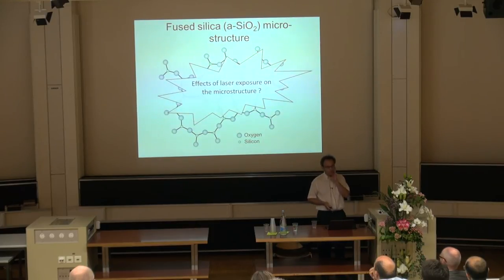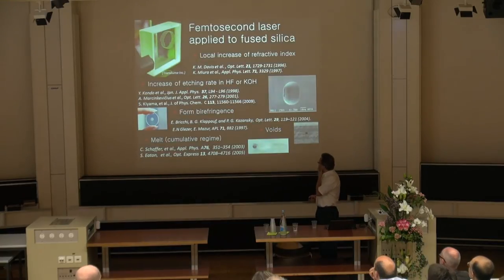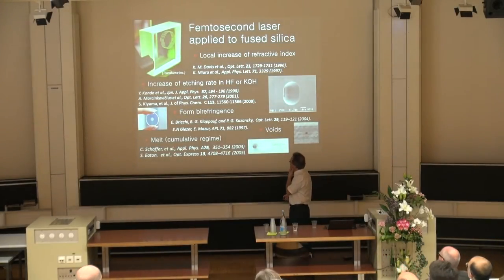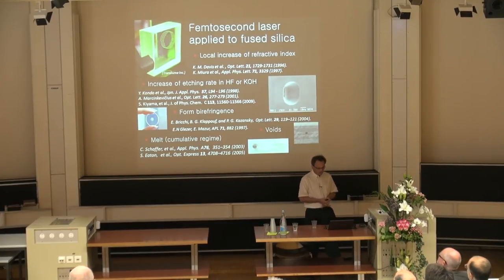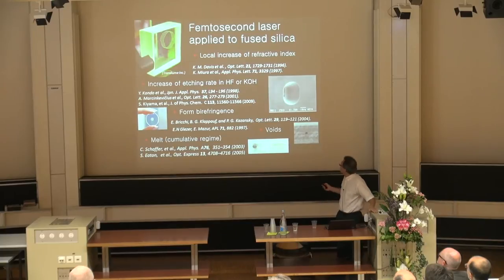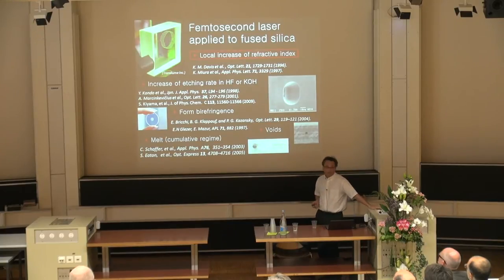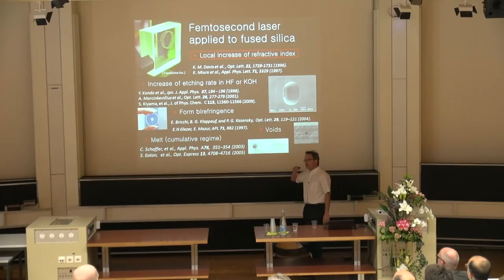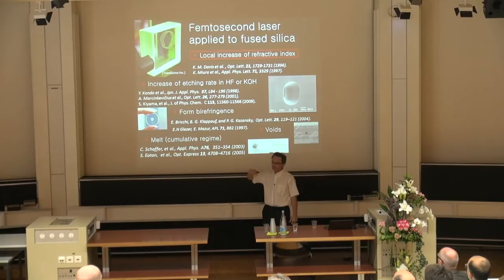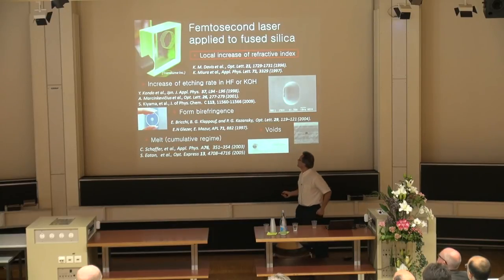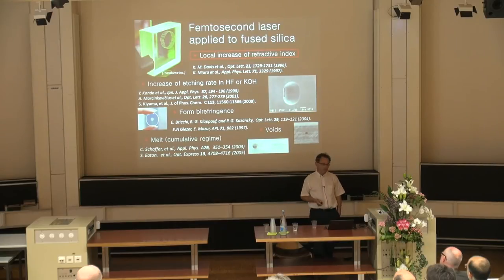Okay, so now the question is, what happens if we expose our femtosecond laser on this structure? Well, it's very nice, in fact, because a lot of interesting things happen from the viewpoint of making microsystems and integrated devices. The first one is that you can increase locally the refractive index. So it's like if you were capable of writing a fiber inside the volume of a glass. So that's very interesting. You can see, for instance, here, these helicoidal waveguides, which were made in a block of glass.